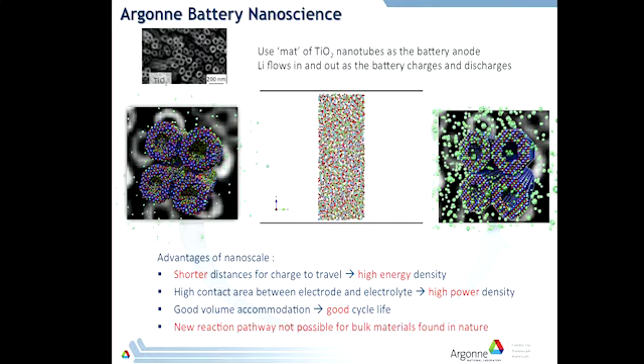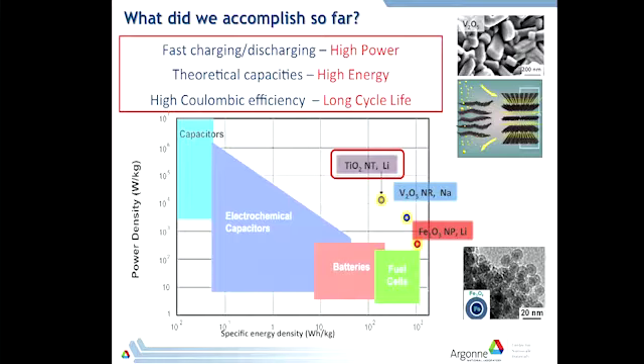And again, by combining experiment and simulation, there was this completely new reaction pathway found, and that will only happen at the nanoscale. You wouldn't see that in a bulk material. And so, by using those titanium oxide nanotubes as the anode, we've been able to put a point over here on that graph. And so we've been able to get a fast charging, discharging battery with a high capacity and a long cycle life. Of course, there's a lot more that has to be done. This is very fundamental studies, and so this has to be now made into a device. But that all can go forward.